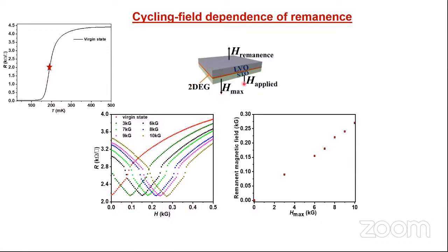And because the H max, the cycling field, was applied in the negative direction, the remanence is in the positive direction. And we see that this minimum, which gives me the remanent magnetic field, is a function of H max, the maximum field up to which the cycling was done. So if you give me a sample by doing some field cycling and not telling me at what field it was cycled, I can do this measurement and, from the value of the magnetic field where this dip appears, I can tell you at what field the cycling was done.